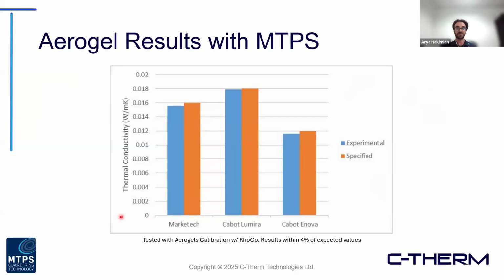So I wanted to start with a very basic, simple example, which is room temperature measurements of some aerogels that were measured using MTPS. These were some commercially available samples that were tested, all found to be within about 4% of the reference expected values. So there's certainly quite a clear fit here for some very basic testing. But this is, of course, just that: very basic, room temperature, setting up, doing some quick testing.